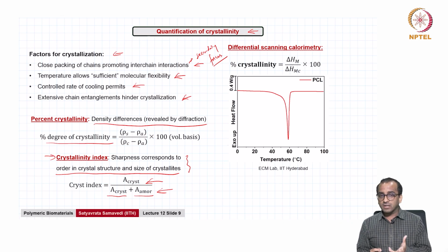So, as you are heating it, if you want to keep both pans at the same temperature, and the sample, the polymer, in one pan undergoes a transition like melting or crystallization, that might involve removing or adding heat. And by tracking how much heat is added or removed such that both pans are maintained at almost the same temperature, you can get access to things like melting enthalpy.